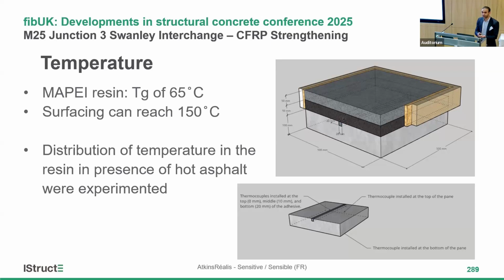Because of the shortage of information, we had to check, especially because there are 2 layers of hot rolled asphalt, which is going to be laid on top of the strengthened element along with the resin. So this resin should not reach the glass transition temperature, because if it does, then it is not effective and not participating in the load carrying capacity. So what we did is we cast a 500 by 500 mm slab. A groove of 20 by 20 was executed and the strengthening was carried out.